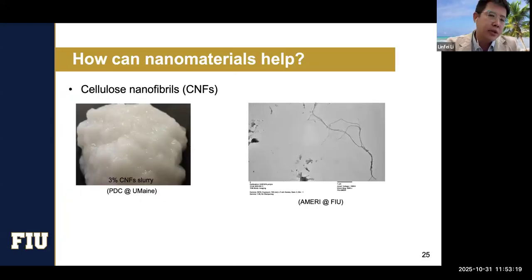So how can nanomaterials help? Here we want to introduce one type of nanomaterial we'll be using specifically for internal curing. It's called cellulose nanofibril, so people also call it CNF. As you can see, we took this image. We got cellulose nanofibril from the University of Maine, PDC, the Process Development Center. This is 3% CNF slurry with 97% water. And it's more like a gel, or a cream. So you can imagine how this material can hold water.